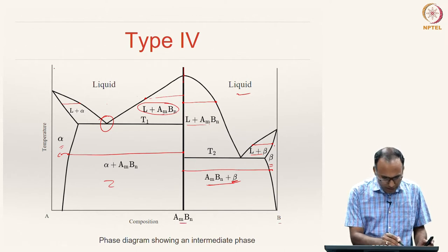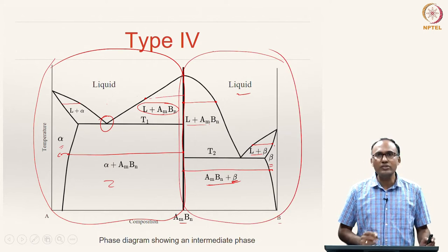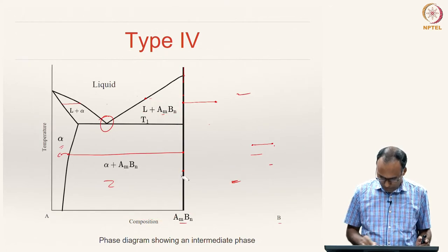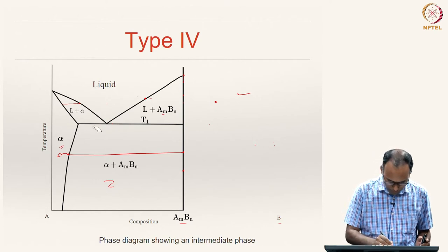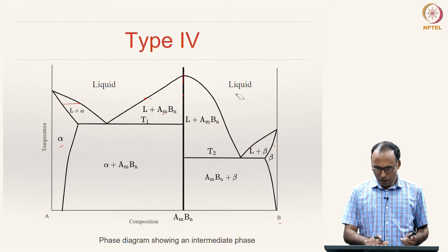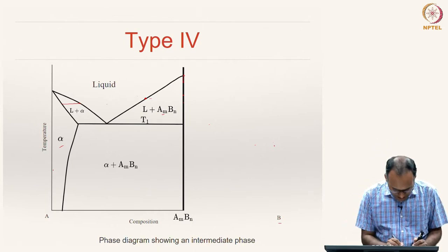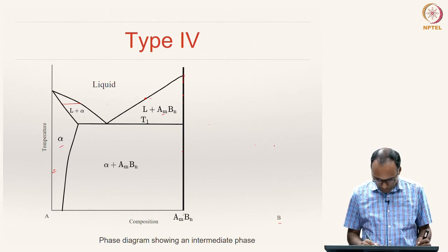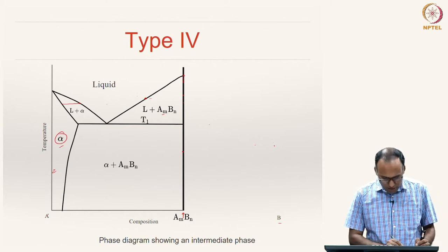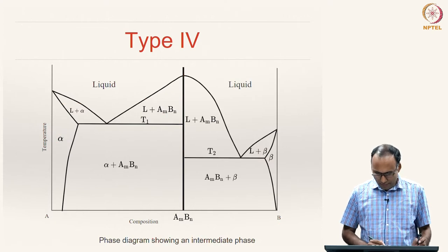You can actually see only the part from A to A_M B_N as one system, and A_M B_N to B as another system. So this is one phase diagram and that is another phase diagram. As shown before, this is the complete phase diagram. If we blank the right-hand side, it looks very similar to our Type 3 alloy on one side, but on the other side it has zero solubility—like a pure solid. You can think of this as a system which has some alpha solid solution on one side, but on the other side there is no solubility of A in A_M B_N.